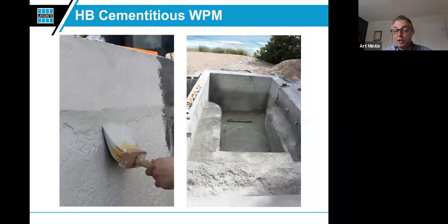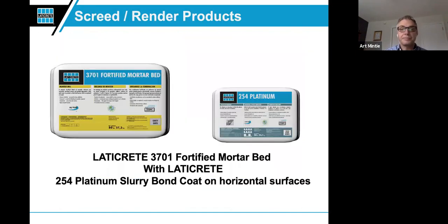Here's a great example of a low-lying area tank. It is literally yards away from the beach. So look at how damp that tank is, right? So there had been seepage, obviously. It was not completely watertight. So they pumped out the water and they were able to apply the cementitious Hydroban first to make sure that there's no intrusion of moisture into the tank. Once we have that in place and we're fully dry, then you can start your leveling process.